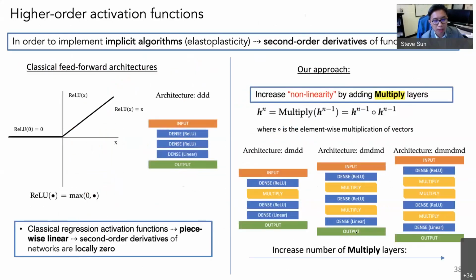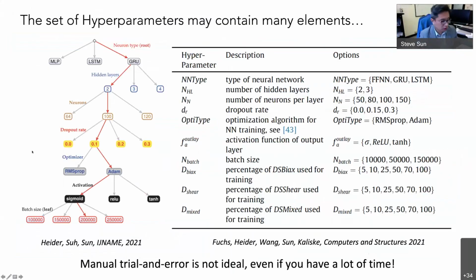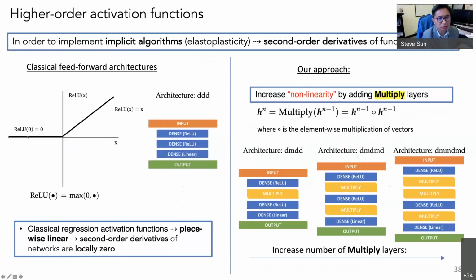Also, for the level set training approach that we introduced, one of the important things is that it demands a degree of continuity. While we can choose the hyperbolic tangent activation function to enable that, what we found out, at least empirically, is that using ReLU seems to be a good choice if we introduce an additional multiplying layer to increase the degree of continuity. So the idea is very simple.